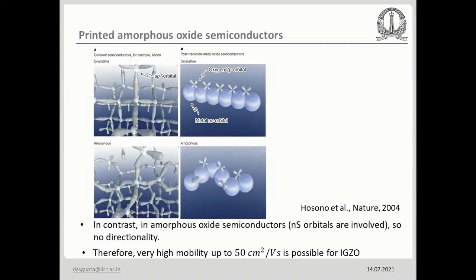In silicon, it was 200 to 300 centimeter square per volt second for polycrystalline. Single crystal is 1400. For amorphous, it's 0.5. But for oxide, indium oxide was 100 centimeter square per volt second, or 200. For amorphous IGZO, indium gallium zinc oxide, which I have written here, it is also 50. It doesn't degrade that badly, and there are advantages if you go for amorphous.